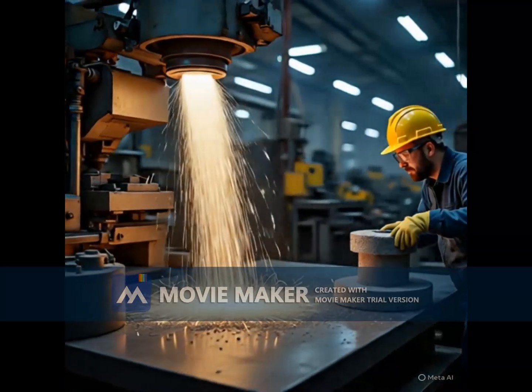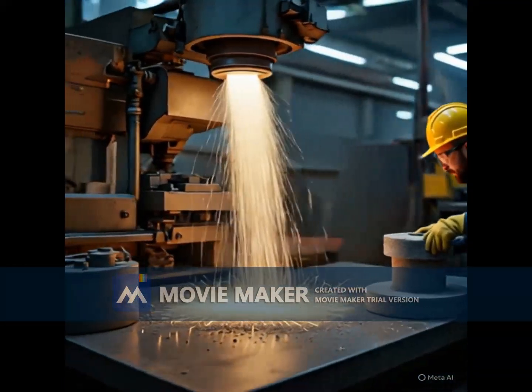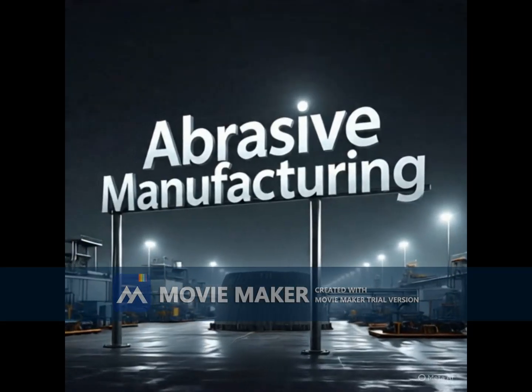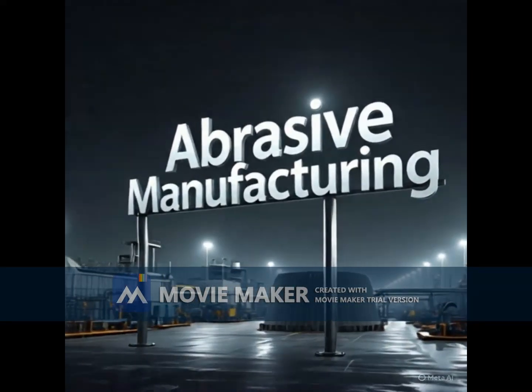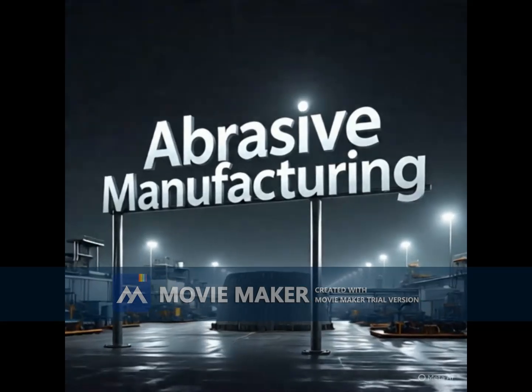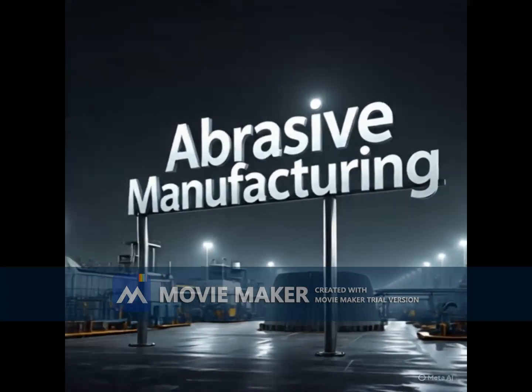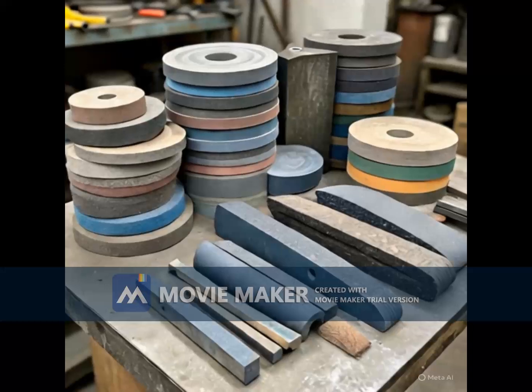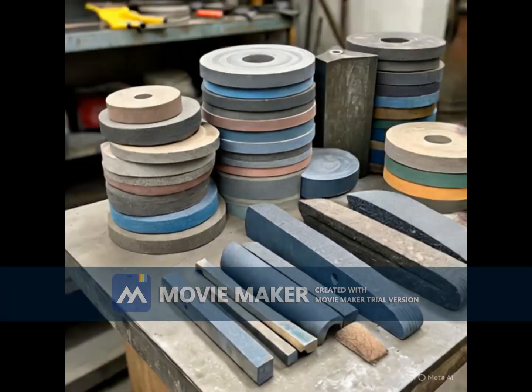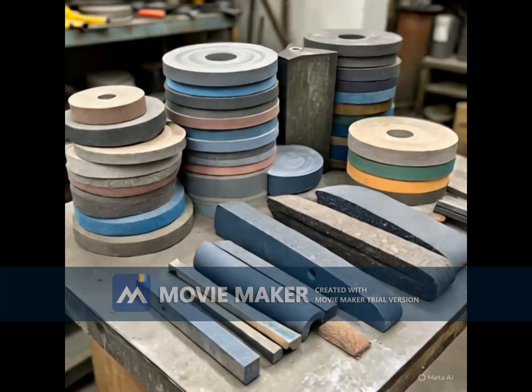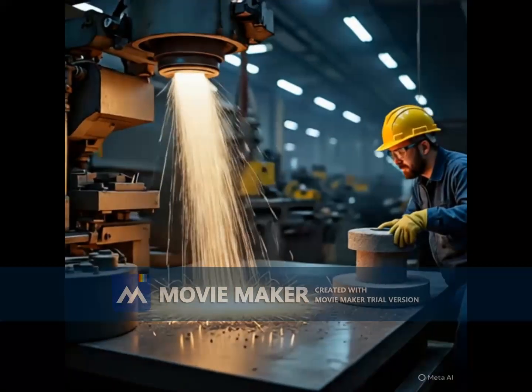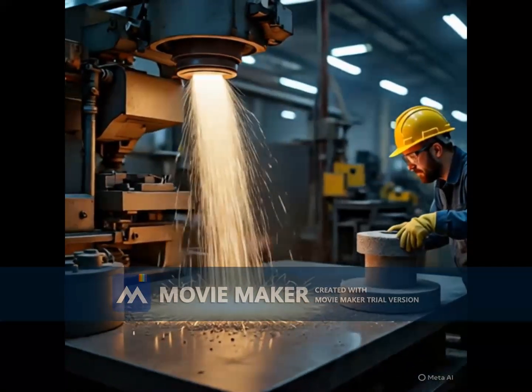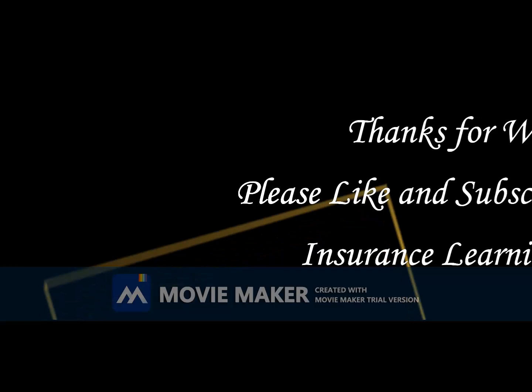Forming the abrasive tool. Bonded abrasives: mixing abrasive grains with binders; pressing into molds; curing in ovens, resin bonded, or firing, vitrified. Coated abrasives: applying adhesive to backing, paper, cloth; electrostatic coating of grains; drying and curing. Super abrasives: high temperature sintering of diamond or CBN with metal or ceramic bond.